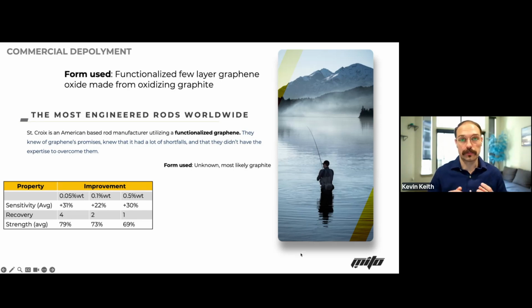And so when we were put into their system, they have their own internal testing to where they test sensitivity, recovery, and strength. All three of these tests are on a rod within a dynamic scenario. So when they test sensitivity, they hook them up to extremely sensitive load cells, and they have a pneumatic hammer hit it, and they measure how the frequency moves back and forth and how much time it takes to reset to zero. The recovery method, what they do is they hook it into an anchor, they load it to a predetermined amount, and then they let go, and then they measure how fast it goes back to zero. So that one's more of a tournament style bracket. And then strength, they hook it into a dynamic load cell to where they simulate hook setting at varying degree angles. And so by the time you're able to calculate how much momentum force is going into the system, that's how much extra strength is being calculated.